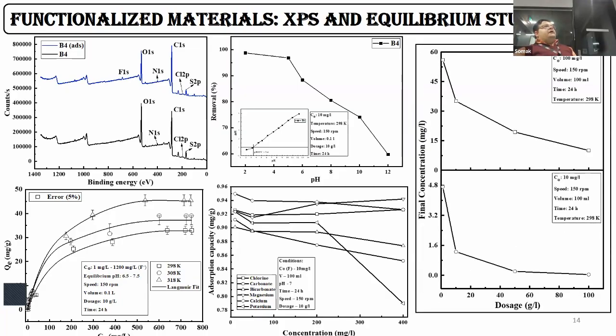We carried out analysis with the effect of dosage as well, done mainly with two concentrations of fluoride, at 10 milligram per liter and 100 milligram per liter. At 10 milligram per liter, we can see that at 50 gram per liter of the dosage, it is actually getting saturated. So you can use something about 50 gram per liter where these beads can completely remove fluoride.